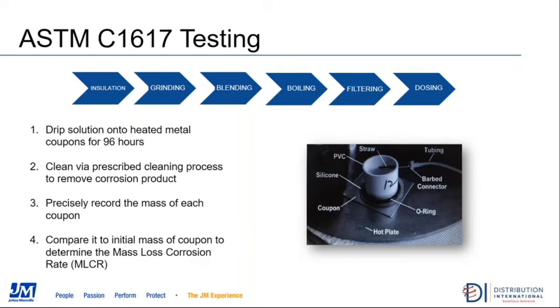So let's take a look at the first of these, and this is the ASTM test protocol C1617. This is a very detailed procedure for how you prepare and conduct the testing. If you look at the graphic on the right-hand side, you see a small metal coupon sitting on a hot plate, and on top of that coupon is a small piece of PVC pipe that is sealed to the surface of that coupon with a silicone sealant and O-ring, and then connected to the PVC pipe is a tube and a straw, which is used to introduce liquid into the test configuration.